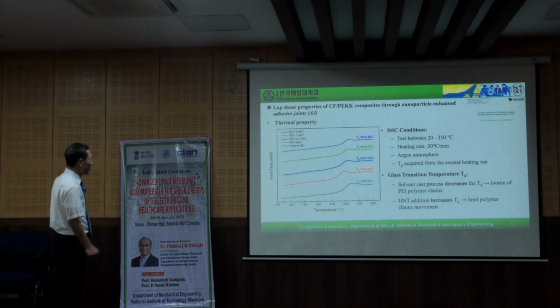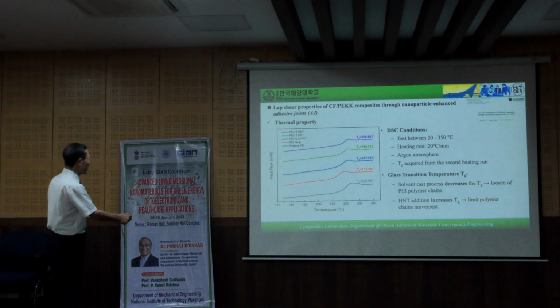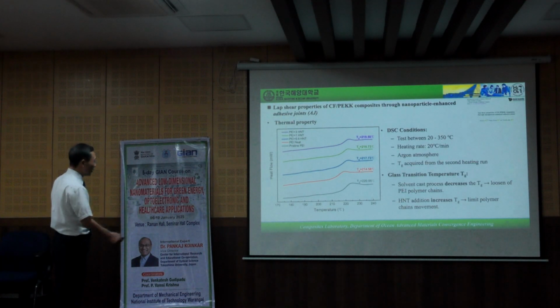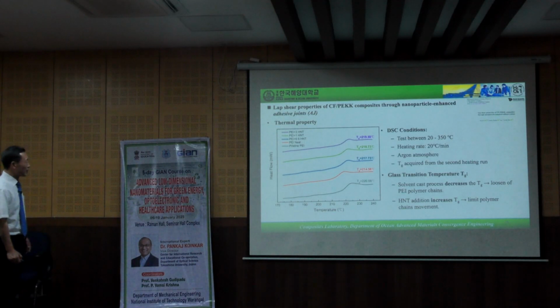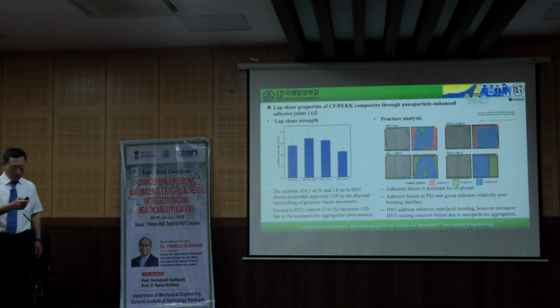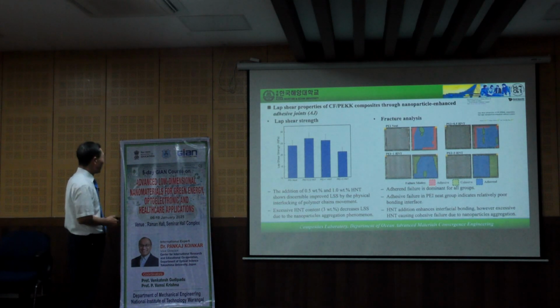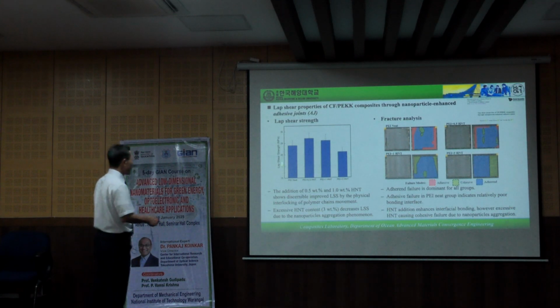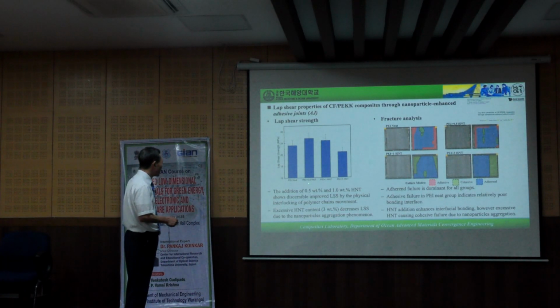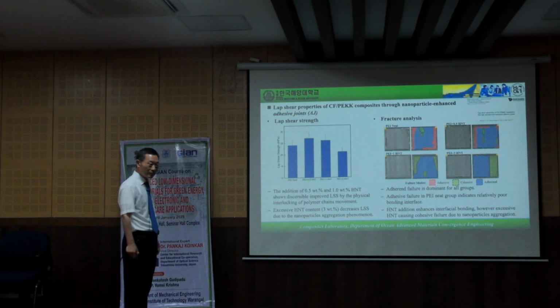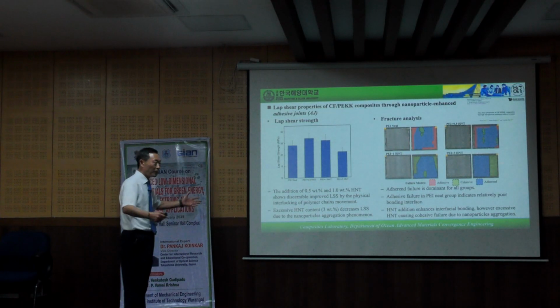We check the thermal properties. Tg will be changed against the PEI 3% and 1%, 0.5, and PEI neat. You can just look at the Tg. Check the DSC conditions and glass transition temperature. Also, we performed the lap shear strength test through nanoparticle enhanced adhesive joint. The lap shear strength for 0.5 HNT is the highest value shown. This is the main result here.